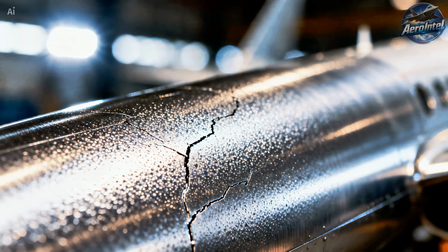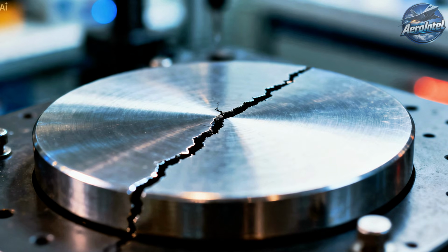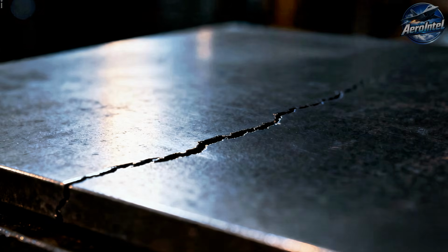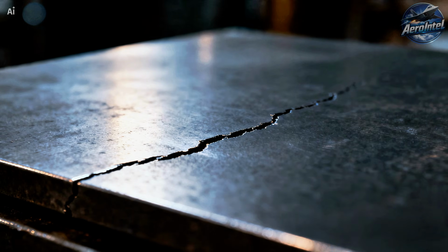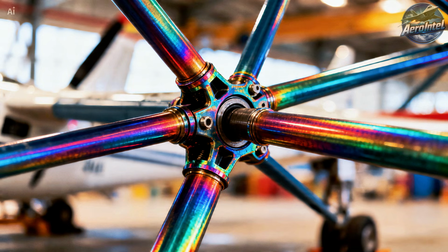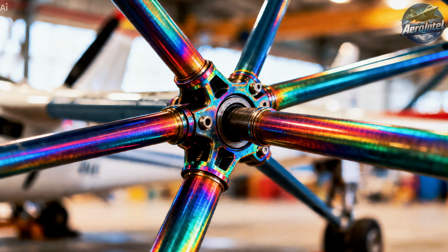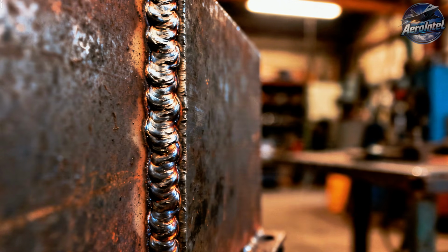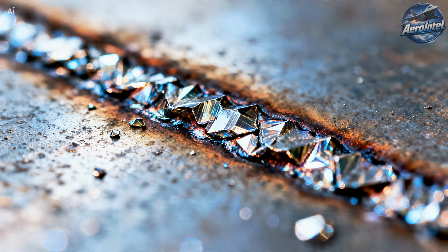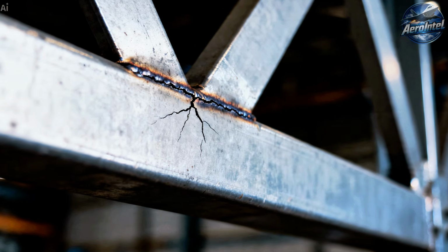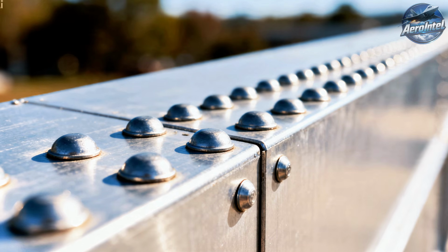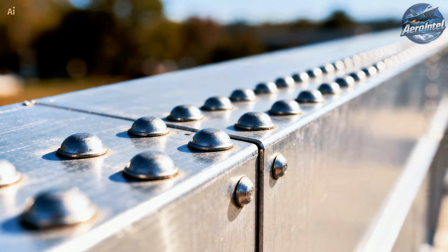Under repeated cyclic stress, metals crack. Not from being overloaded once, but from the slow, progressive initiation and growth of microscopic cracks, usually starting at stress concentrations. Those concentrations? They love welds. The heat-affected zone, the residual stresses, the grain boundary disruptions, they are prime real estate for fatigue cracks. But here's where rivets have a physical trump card: crack arrest.